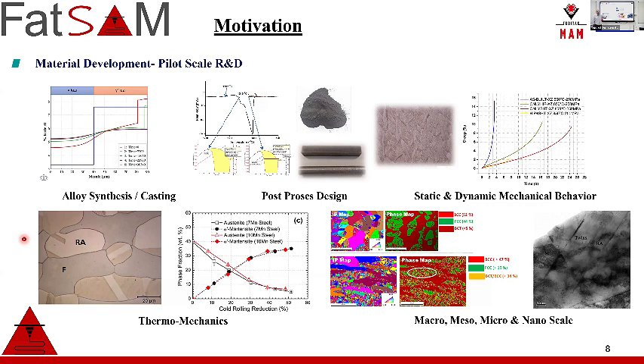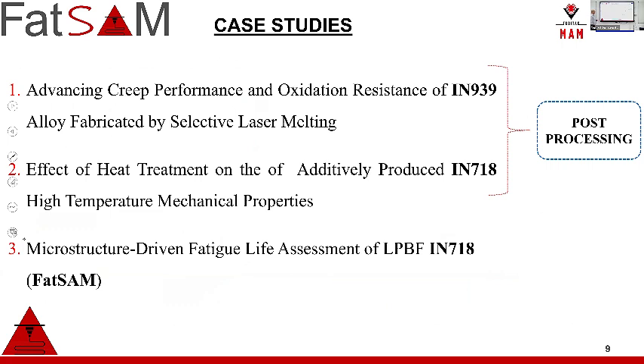So we use some thermodynamic simulations. We are experts in thermodynamic simulations. We design heat treatments in certain cases using hot compression and torsion tests and figure out the interface times. We are also trying to do some rolling and forging process parameters. But at the end of the day, we are trying to obtain the final microstructural properties so that we can get better mechanical properties. So for these studies, the first two are already completed projects for certain aviation industry.